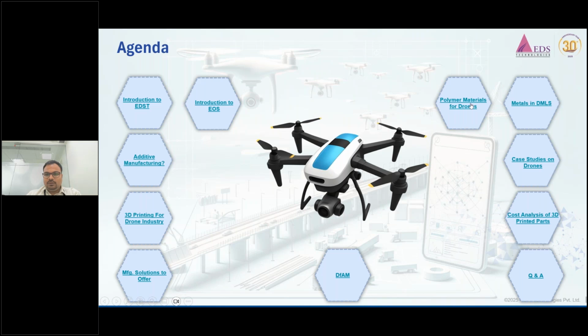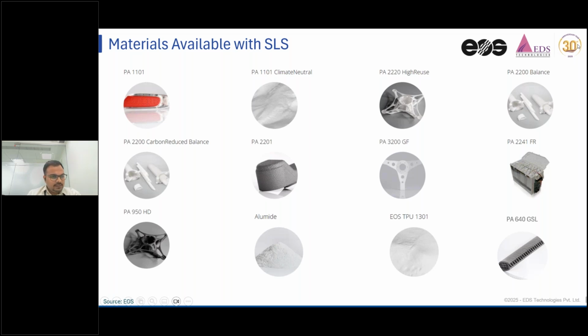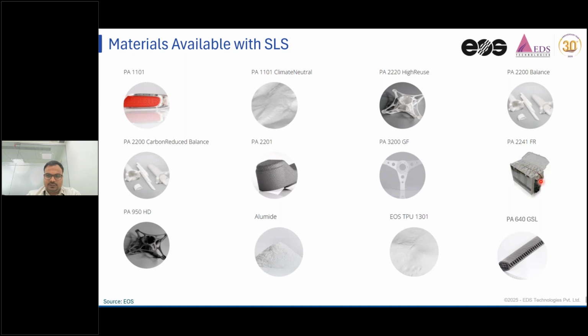Now let's have a look at all the polymer materials that we have in SLS. We have nylon 11, we have nylon 12, and different other grades and subgrades of nylon 11 and nylon 12. In nylon 12, we have glass filled material, and we have FR material, flame retardant material tested for many applications. You can use it for your drone applications, where flame retardancy is a concern, or if you want to use it for your battery pack, you can opt for it. And then we have the newly launched PA950 HD, which comes with the highest reusability. It is 80% reusable, so we'll talk about it later. And then we have a composite, a polymer and metal composite, which is alumide. It's a mixture of nylon 12 and aluminum.